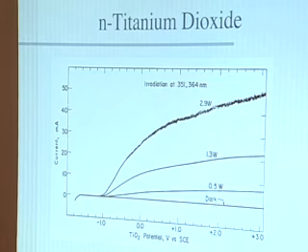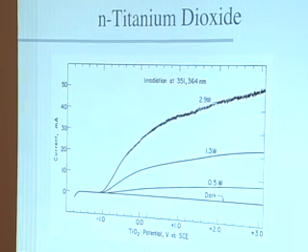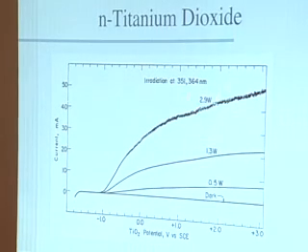Everybody's favorite is TiO2. So here's non-dye-sensitized for those that care, TiO2, the real thing. And again, operating at these high intensities. And once again, you can see when I have band bending available, I separate charge and I generate oxygen. And as I go to higher intensities, I generate more oxygen and the light starts to scatter. I get a flat band potential right around here, and all of these, whether it's in the light or in the dark, will reduce water when I invert the bands over here.